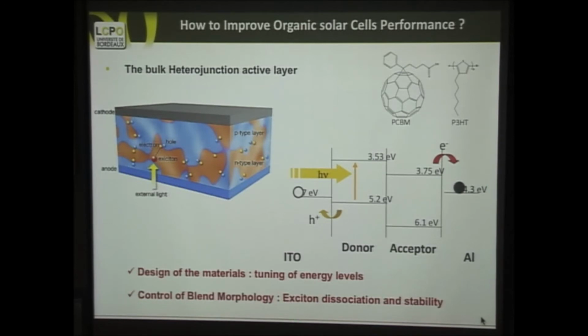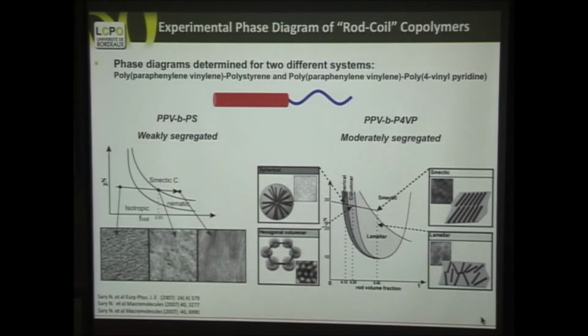So, and then you have to control the morphology, as I just showed you, again to make the material stable, and also to dissociate the excitons. Here again we go. Here we have block polymers, but this time different ones a little bit. This one is rigid, and this is flexible, simply because we put this conjugation, the simple double bonds, and the molecule becomes stiff. So you have rods. And since you have rods, then the rods interact also in this way, or in this way. So we have to take into account this kind of interactions.